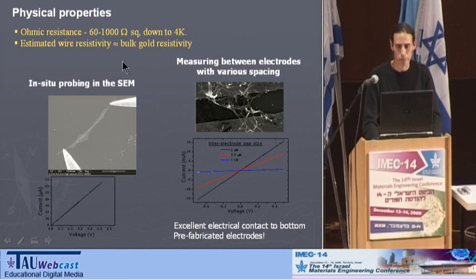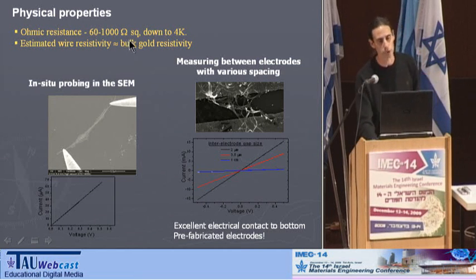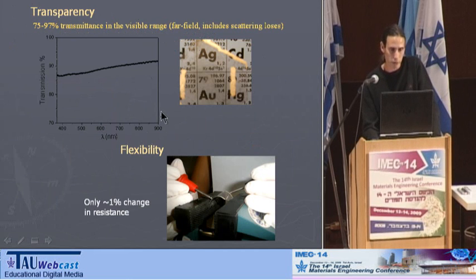And now, in terms of sheet resistance, I would say that in general, the sheet resistances that we obtain are now in a fairly broad range, because we still make the films using different techniques and different parameters. So they are typically between a few tens of ohms per square up to, let's say, 1,000 ohms per square. Now, the transparency of the films is, I think, fundamentally very high. We are now getting numbers as high as, I think, 97%. Here you see something more typical that is, let's say, around 90%.